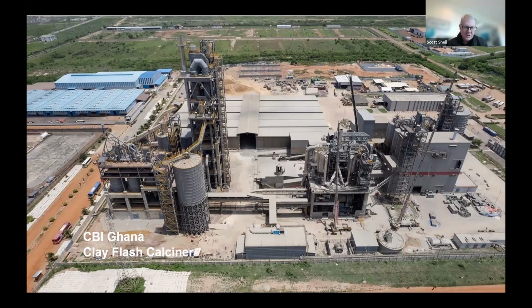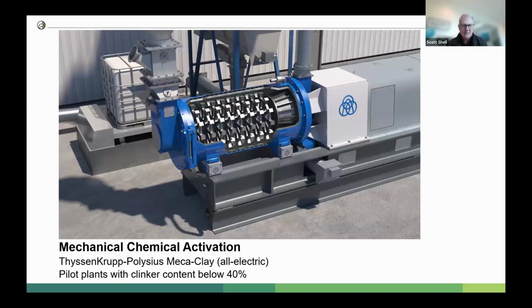There's a new technology that's just coming out that's called mechanical chemical activation. And this is the ThyssenKrupp Polysius MechaClay. They've just gotten several awards from the EU Innovation Fund to develop this new type of technology. They're building some pilot plants using this process, which is lower carbon than the thermal conversion process in the prior two examples. And they're targeting below 40% clinker. So it's a continued progress to keep lowering the carbon content of these materials.